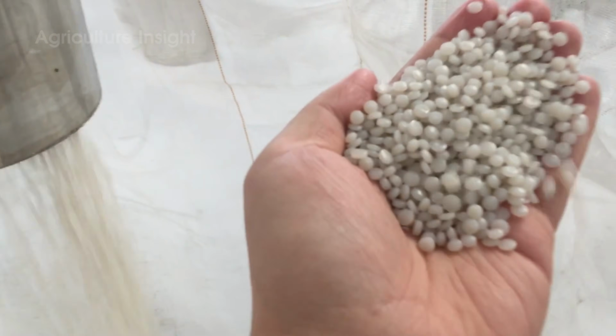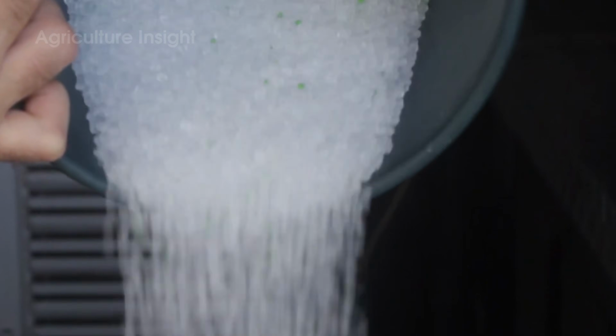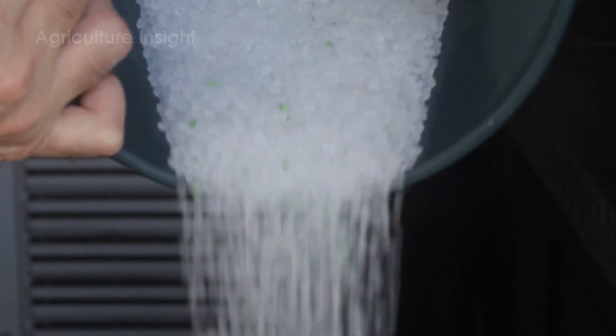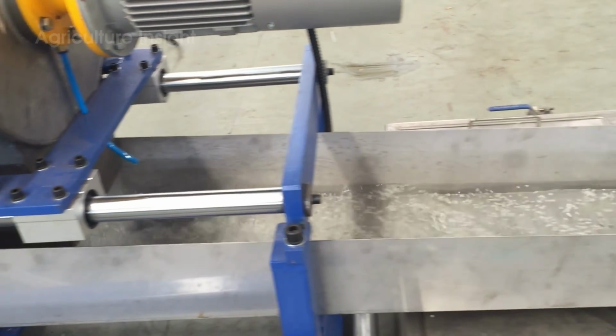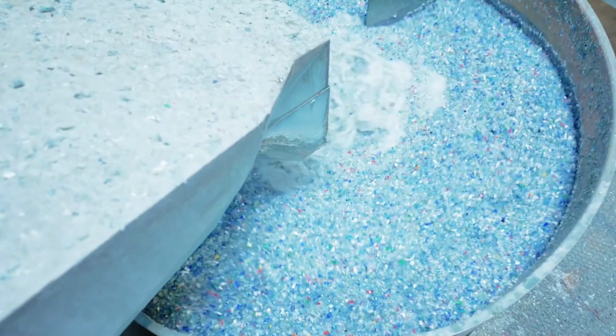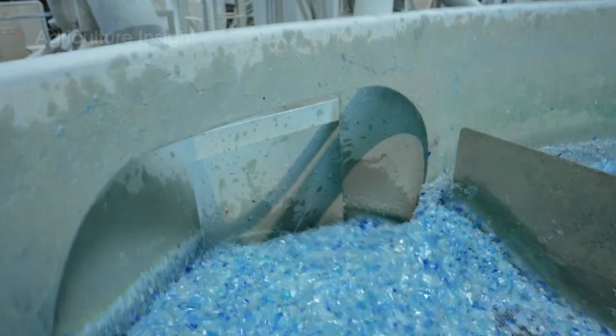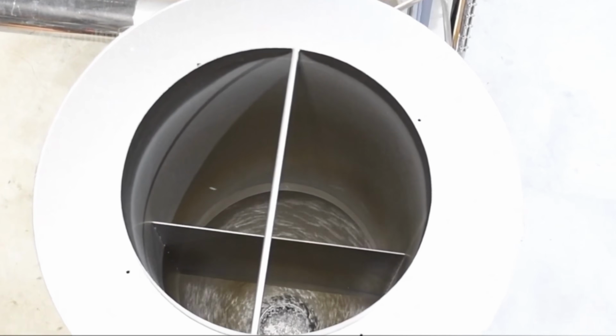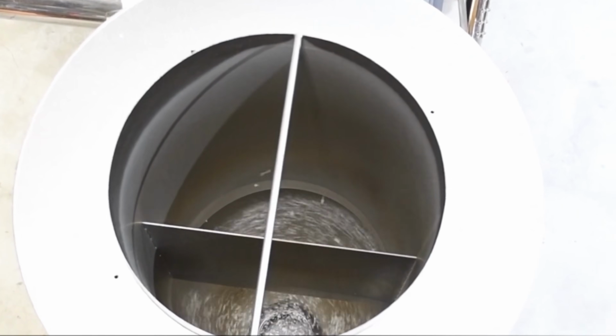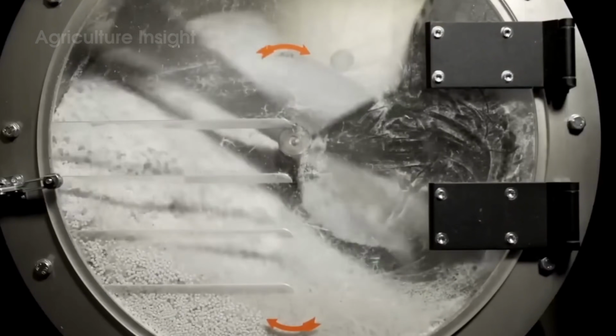As the plastic travels along the length of the screw, pressure gradually increases, forcing the melt forward. When the material reaches the desired viscosity, it is pushed through ultrafine metal screens that trap the final impurities. At this stage, the molten plastic is cut into countless tiny pellets and immediately cooled with water to solidify their shape. Uniform in size, smooth-surfaced, they sparkle like gems.